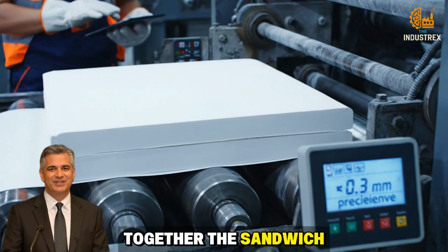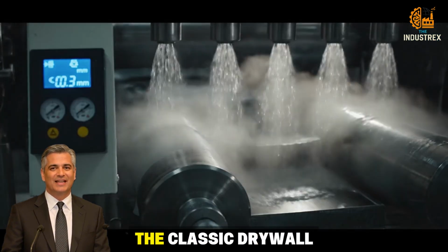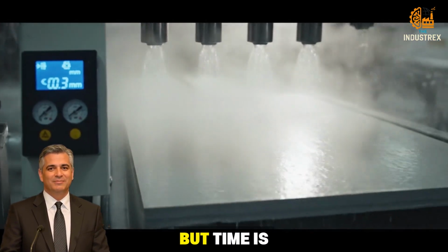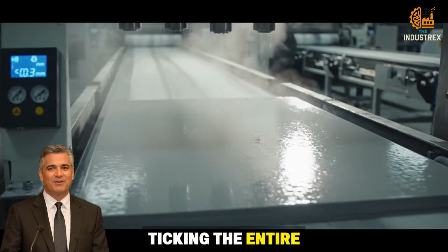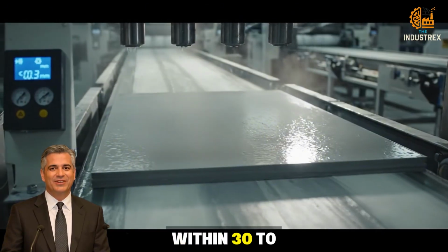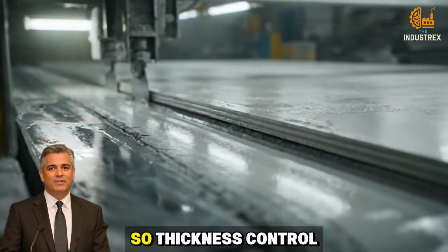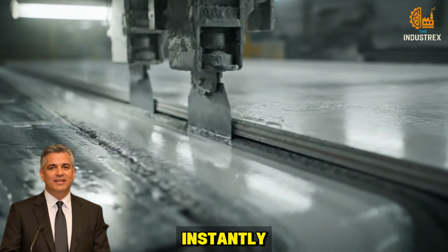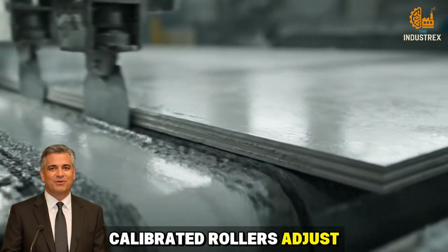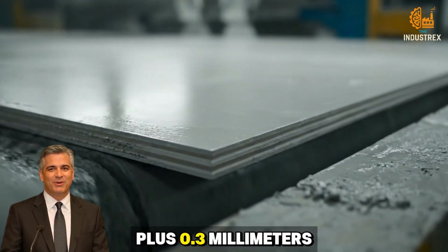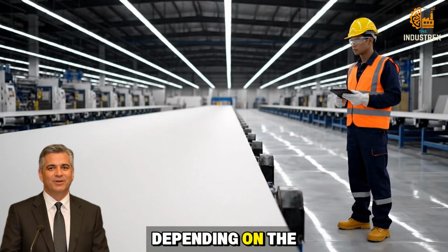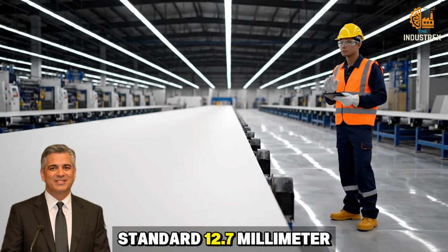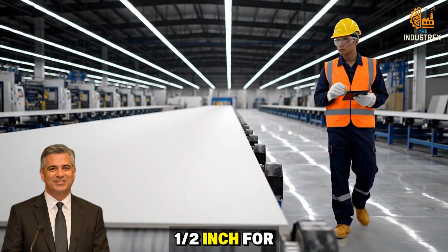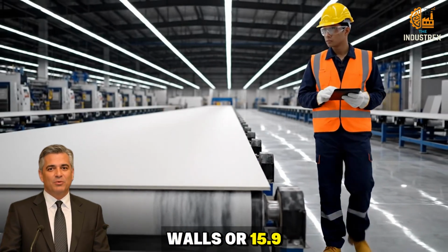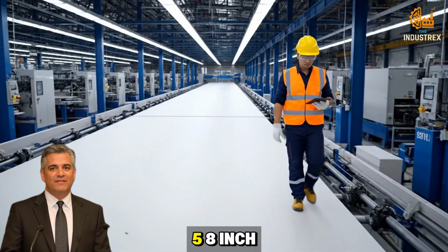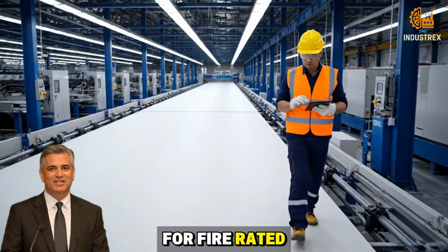Together, the sandwich of paper and gypsum forms the classic drywall panel structure. But time is ticking. The entire mixture begins to set within 30 to 60 seconds, so thickness control has to happen instantly. Calibrated rollers adjust the profile to within plus or minus 0.3 millimeters, depending on the product type. Standard 12.7 millimeter, 1/2 inch for walls, or 15.9 millimeters, 5/8 inch for fire-rated sheets.